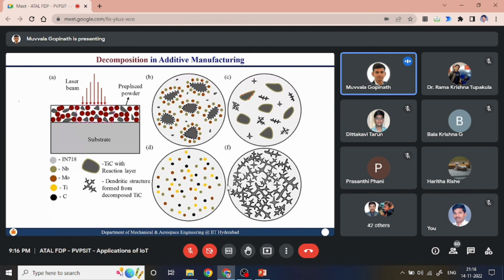So when you look at your time temperature history, the solidification shelf will correspond to your Inconel 718 only, because your titanium carbide is not melting, so there is no change in the chemical composition, hence there will not be any shift in your solidification shelf. But assume that you have given a lot of molten pool lifetime so that it decomposed. This is the wetting. So this is the shell core structure. So this is the wetting layer. If you give much more time, they will decompose and they will form dendrites. The moment they decompose, the chemical composition of Inconel 718 changes. So no more will this solidification shelf occur at the same location.